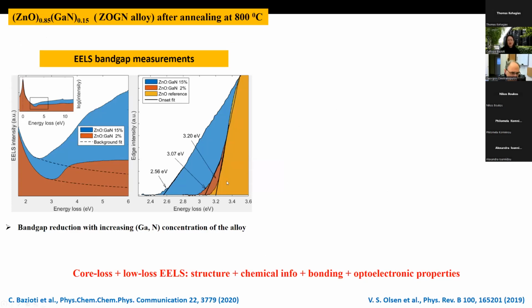At first, you can see a comparative study that we did, first measuring the bandgap in pure zinc oxide, and then comparing films with different gallium and nitrogen concentrations. You can see that by increasing the concentration, we have a gradual reduction of the bandgap. For 15%, we reached 2.5 eV.